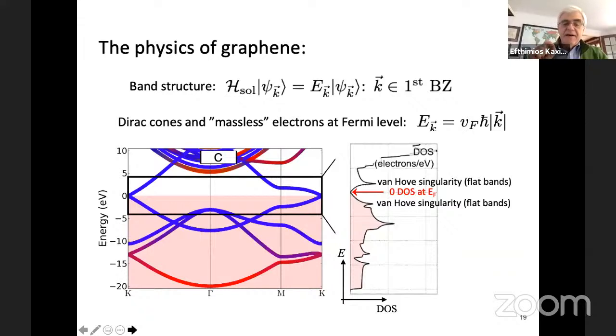Another really important quantity that we will be following is the density of states. So imagine here that on this axis now, I plot how many electrons come from these different bands. So this band contributes a certain number of electrons, this band more, and so on. So this curve shows the density of electrons, the number of electrons, as a function of the energy. And right here where the Fermi energy is, there are zero states, no electrons here. That's why I mentioned earlier that graphene is a poor metal. There's no gap separating occupied and unoccupied states, but there are no states at the Fermi level. So it's a metal, but it's a poor metal.